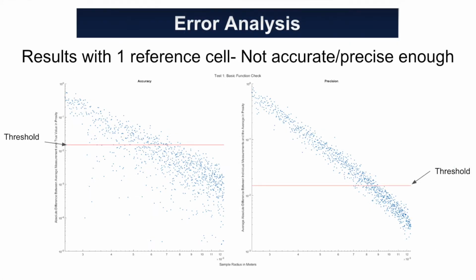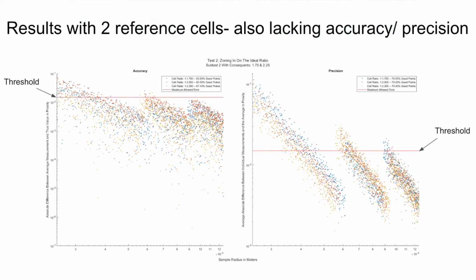We modeled our system in MATLAB and then used error analysis to find the best design to fit with our sponsor's requirements. In this regard, we looked at the system's accuracy and precision. Accuracy was measured by running 10 simulations on a single sample and comparing the mean porosity measurement to the true value. Precision was measured by comparing each of those simulations to the mean and finding the average of that difference. Ultimately, we wanted both of those to be under 0.015 porosity as per our sponsor's requirement.